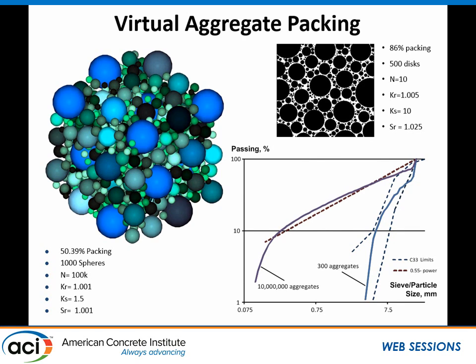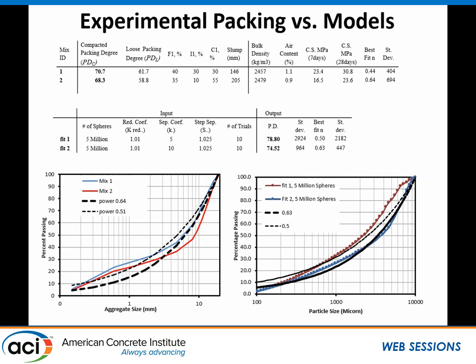If you introduce those, it then asks you for the number of particles as well and how many trials you want the algorithm to run to be able to fit the next aggregate within the previously packed aggregate. If you do that, you get gradings like that for 2D, for a limited number of aggregates, and then for up to 10 million aggregates. And then you can compare those to ASTM. What this does for you as a tool is, instead of running an unlimited number of experiments, you can play with those and get to real-world aggregate gradation and compare those to whatever you want to compare it to.